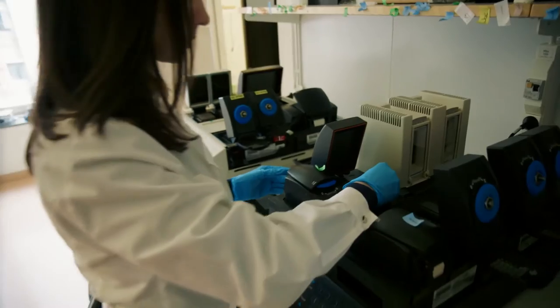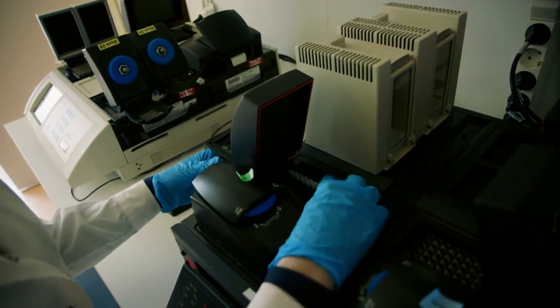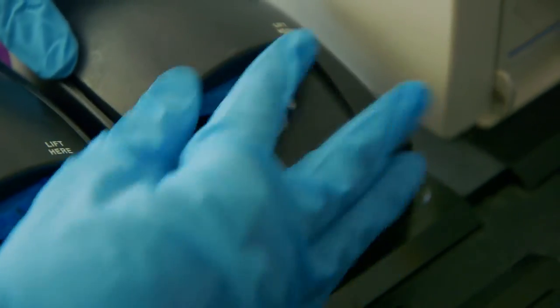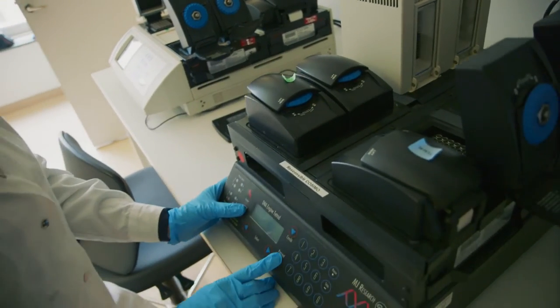What we do is take all of those samples and pool them together with a pipette. Then we put it on a thermal block, heat it up and cool it down overnight, and then we have the folded structure — everything folds by itself in the test tube.